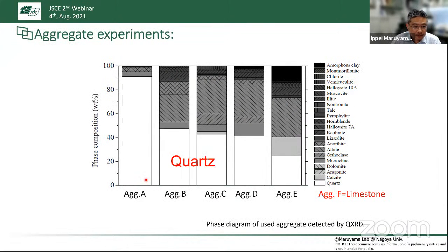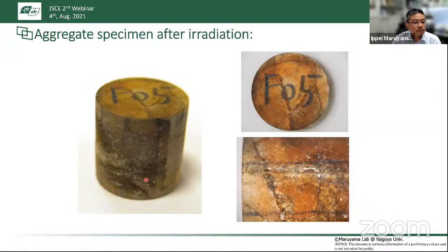As I mentioned, 6 concrete aggregates were irradiated and the length change measured. Five aggregates are sandstone, and the last one is limestone. Our working hypothesis was that quartz is sensitive to the neutron irradiation. Therefore, sandstone aggregates containing different amounts of alpha quartz were prepared. The contents were quantified by XRD Rietveld analysis. And this is how the aggregate looks after the neutron irradiation. We see some minor cracks on the surface of the aggregate specimen.